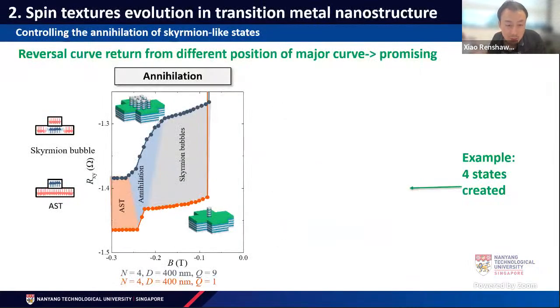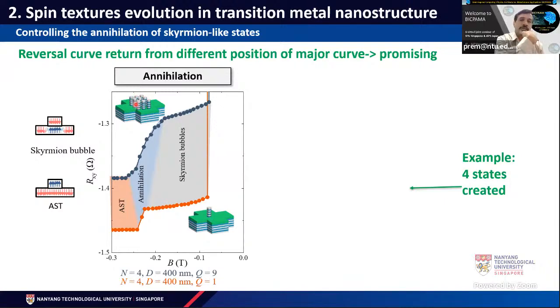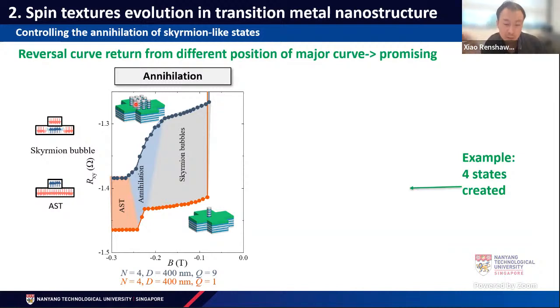I go back to the structure here. This is my understanding of your question: when we measure the device, apparently the majority of the current will go through the bottom layer, because the bottom layer is the layer that's connected to the electrodes. And you're asking whether we can probe the effect of these nanodots on top. Yes, it's a great question, and we also had this doubt before conducting the experiment. We thought if the bottom layer shunts the current, we will not be able to probe the upper layer magnetic